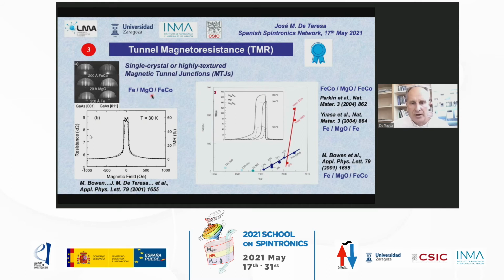At that time we were collaborating with the group of Albert Fert in Paris, and it was possible to pattern these samples and to measure a very high magnetoresistance effect. At 30 Kelvin, this effect was around 60%, and at room temperature, it was 27%. And by that time, 2001, there were some theoretical calculations which indicated that in this iron, magnesium oxide, iron system, it could be possible to observe very, very high magnetoresistance, of the order of hundreds of percent.